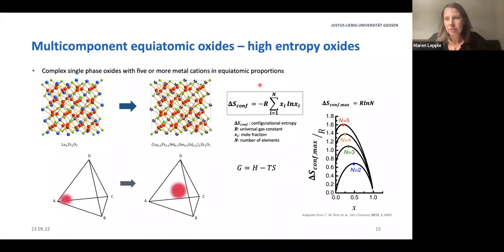So I think if you have a new composition, it's quite important that you also do long heat treatments at quite high temperatures. And then we do XRD, SEM with EDX and EPMA. And I think if you do the long heat treatments and you have phase separation, then you should see it in one of these techniques at least.